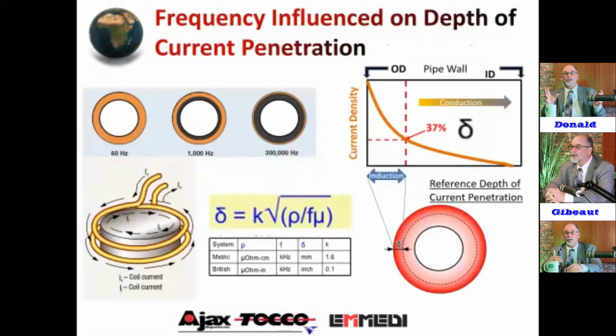Now, as we talk about that current inducing into the tube, frequency plays a major role in the controllability and the heating of induction. And we use a reference point called the reference depth of current penetration, as you see to the right. The definition of that is when the current density reaches 37% of the surface value. And from the time we turn on the induction we're inducing at this depth of current penetration. If you look to the left, 60 hertz, you can see a deep depth of penetration through the wall. 1 kilohertz, 1,000 cycles per second, is shallower. And then you get up into the 300,000 hertz, and it's very shallow on the surface case depth. And again, that case depth and reference depth of penetration is gauged when the current density reaches 37% of its surface value. Well, after that, what happens?